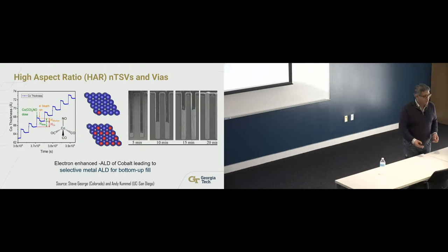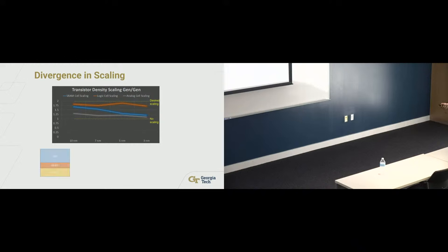So while you're doing your growth, you can actually shoot these electrons, create these nucleation sites, and you can do a bottom-up fill. Basically, instead of having a conformal CVD type process, here you're actually doing a bottom-up fill all the way to fill up these. And cobalt is a great example, because cobalt, in very narrow, restricted geometries, has a resistivity that could even be better than copper. Ruthenium is another story.